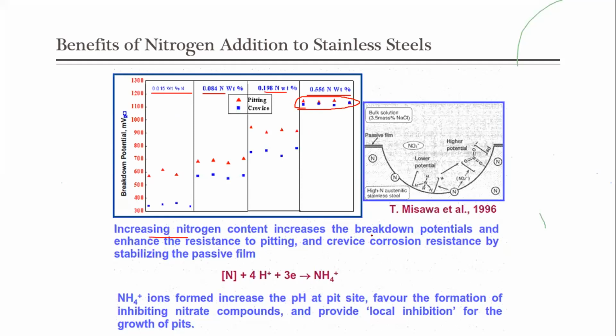If you increase the nitrogen content, the breakdown potential will be increased, which will in turn enhance the resistance to pitting and crevice corrosion by stabilizing the passive film. This passive film will be stabilized by nitrogen. If you add more nitrogen into your alloy, then you will have a strong passive film that cannot be corroded easily. Usually, if you have higher nitrogen content, you can form NH4 ions, which increase the pH at the pit site, which will favor the formation of nitrate compounds and provide local inhibition for the growth of pits. Hence, nitrogen is a very important alloying element in stainless steel.